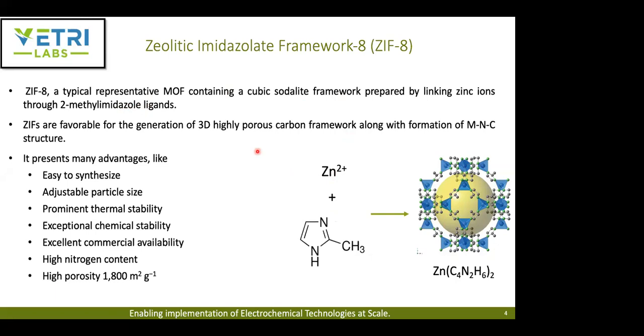The advantage of using ZIF-8 is that it is favorable for the generation of a 3D highly porous carbon framework with the formation of the MNC structure, which is important for good catalytic activity. It also has many advantages: it's easy to synthesize, has an adjustable particle size, has excellent thermal and chemical stability, and has good commercial availability. Of course, they have a high nitrogen content, so you can easily form the MNC structure. And they're also highly porous, with an average surface area of 1800 square meters per gram.